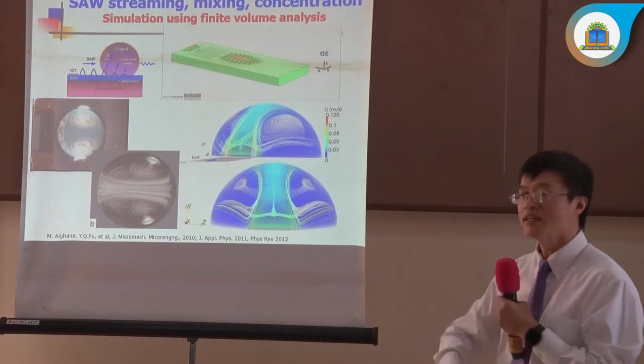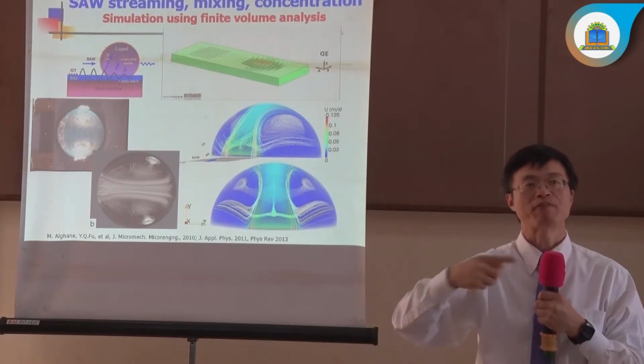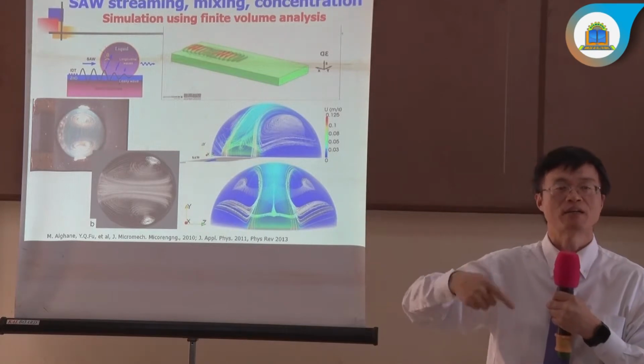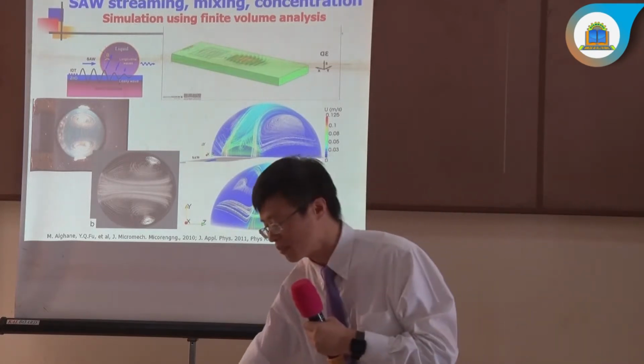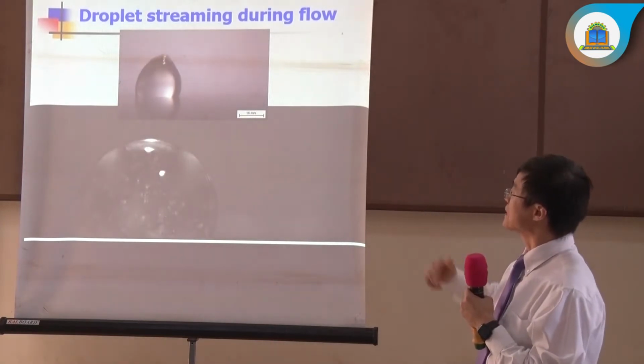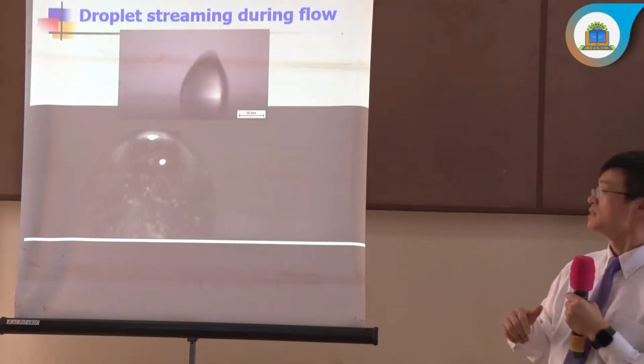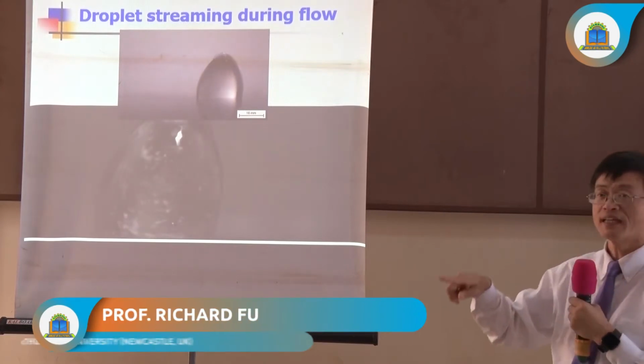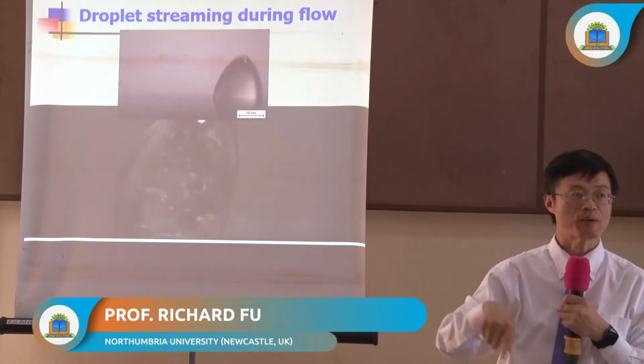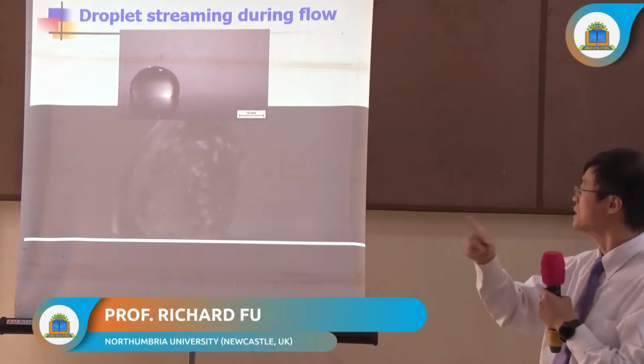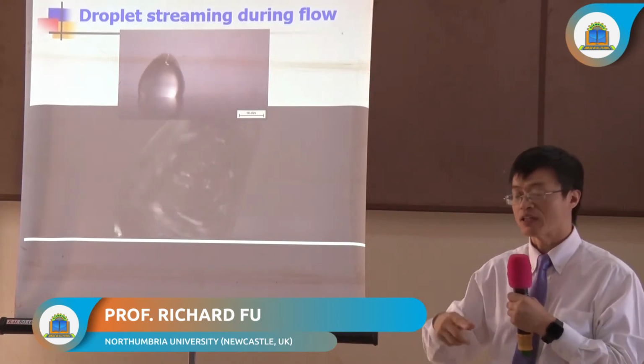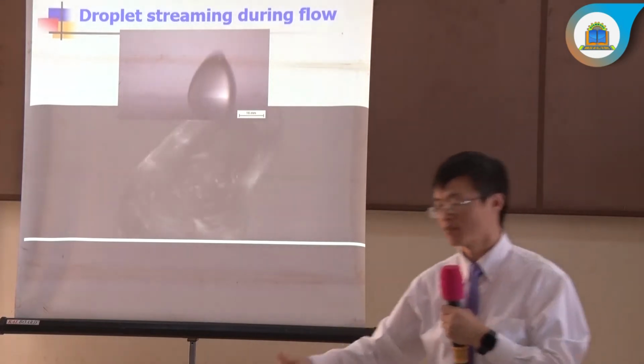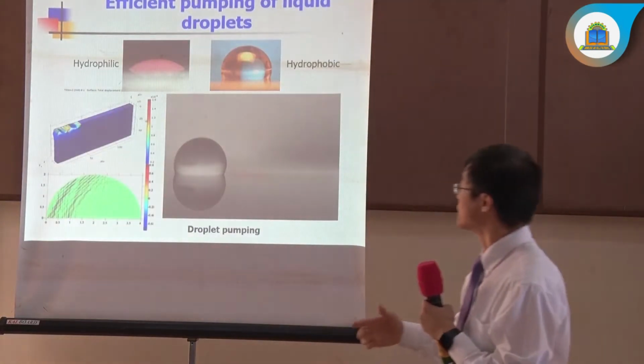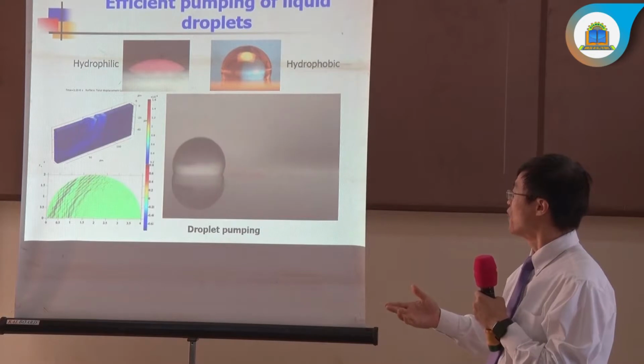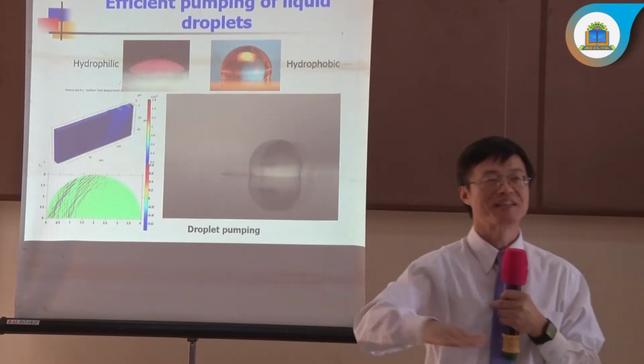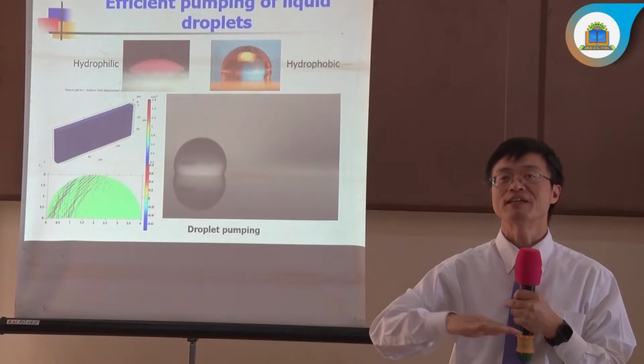So energy will go inside, causing the flowing, we call the butterfly effect. Like one butterfly flowing circularly. If you look at what's happening inside the droplet, you can see that if you have biological cells, the cell will flow together with the liquid. It will gradually pump forward, right? So that means you can realize liquid flowing and pumping. Of course, in this case, we need to treat the surface as hydrophobic, so the liquid flows easily.